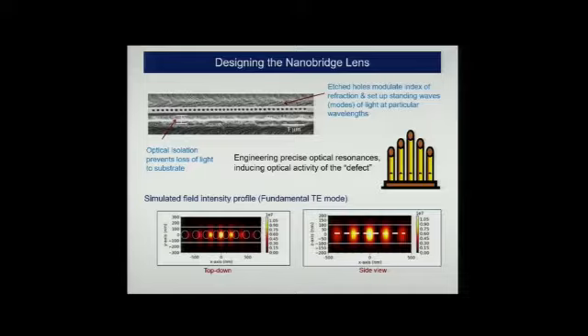To give you a visual view of what it looks like, this is a simulation of the standing wave patterns of the electromagnetic fields for a given frequency. So the dimensions, the size of the holes, the spacing of the holes, all influence the geometry of our instrument. This spatial picture actually corresponds to a frequency picture. We pick a certain frequency where we want resonance, and for that frequency, we have regions of very high electromagnetic field confined to very small volumes, because the distance between here and here is about 100 nanometers.